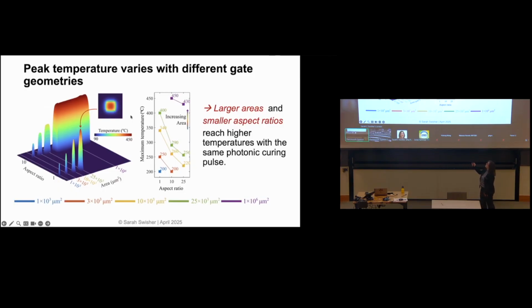And what we can see here is that by changing the area, so going from blue, red, yellow, green to purple, you can see that we're increasing the total area of that absorber. And then these are 3 different aspect ratios. You can see that the maximum temperature might be 200 or it might be 450. For these materials, that is the difference between a device that is phenomenal and a device that is not a semiconductor at all and doesn't work at all. So we designed this experiment specifically to cover this range so that we could show this effect that we were observing anecdotally.